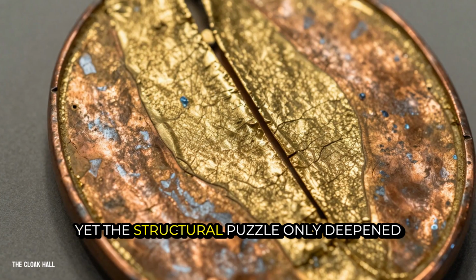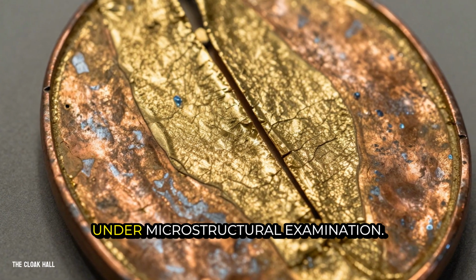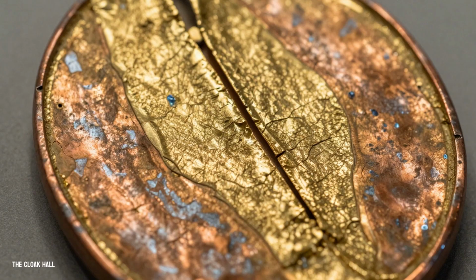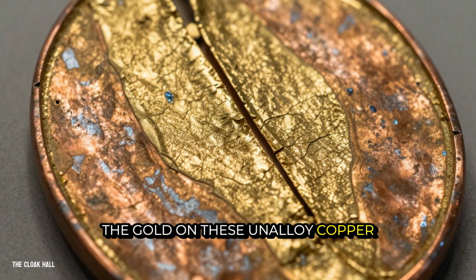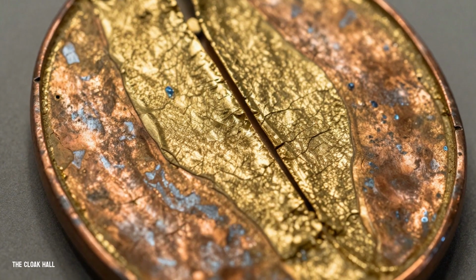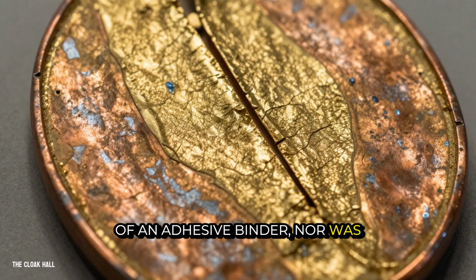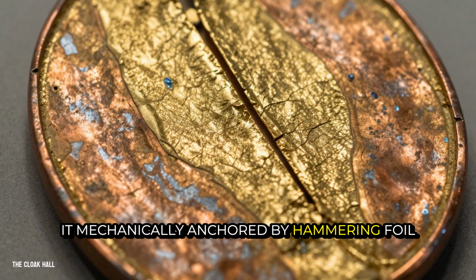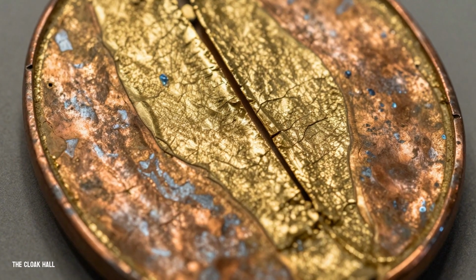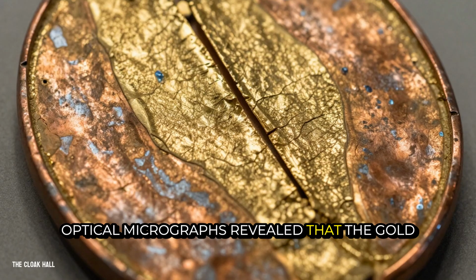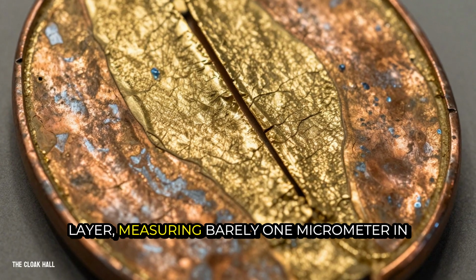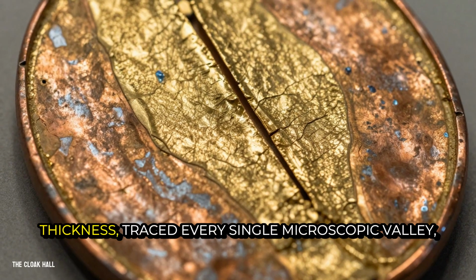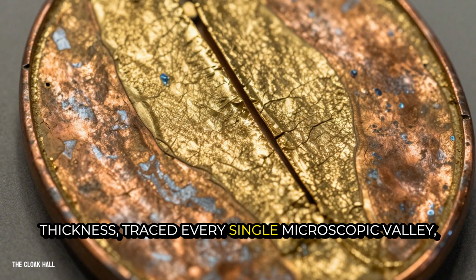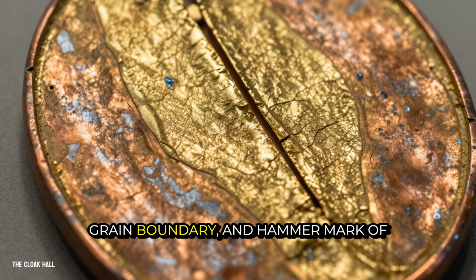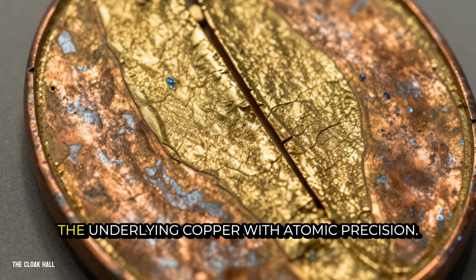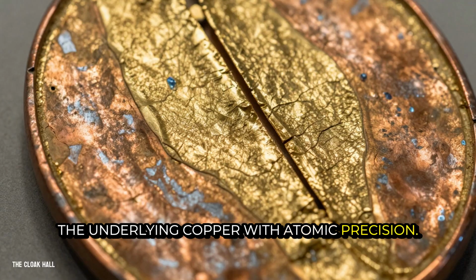Yet the structural puzzle only deepened under microstructural examination. The gold on these unalloyed copper sheets did not sit on top of an adhesive binder, nor was it mechanically anchored by hammering foil into carved grooves. Optical micrographs revealed that the gold layer, measuring barely 1 micrometer in thickness, traced every single microscopic valley, grain boundary, and hammer mark of the underlying copper with atomic precision.